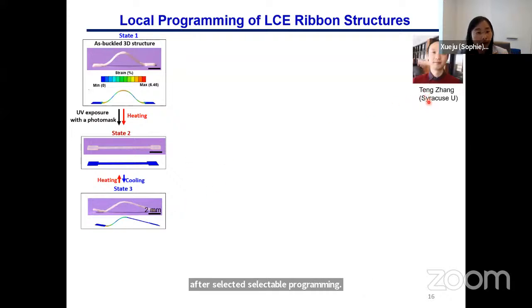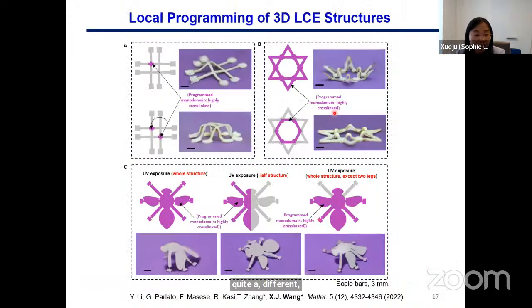The simulation is in collaboration with Teng, conducted using the model change feature in Abaqus. We also qualitatively characterized the mesogen alignment at two locations to evaluate the mesogen programming. In addition, we studied how changing the cross-linking densities and the areas and locations of the mesogen alignment can give us different morphing behaviors and final configurations. We can see that starting from the same original structure, we can obtain quite different final configurations with different stiffness heterogeneities. In addition, the technique can be extended to other more complicated structures as shown here.